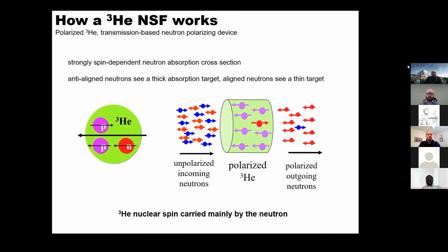And so I just wanted to show you what one of those neutron spin filters looks like. These analyzers, basically you see that cylinder that says polarized helium-3. That contains helium-3 gas. So we're all familiar with the helium that's in balloons, helium-4. This is an isotope of that, and we can polarize this. And when we polarize the helium-3 gas, neutrons that go through it will be polarized when they come out the other side. And so that's how we're able to determine the magnetism of the magnetic structures, by looking at the polarization as they come out. Okay. So that's the measurement technique.